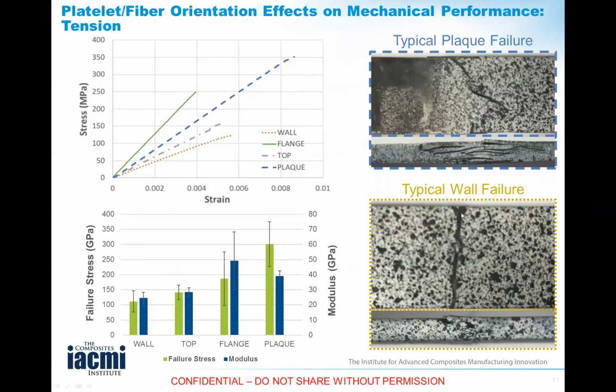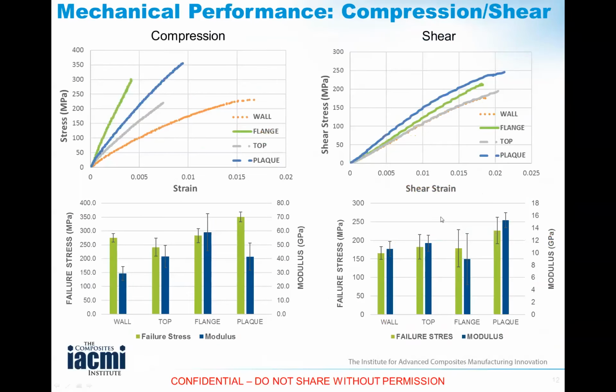So for example, the wall stress strain curve shows that the localization of the failure is very sharp through the thickness and in plane, versus in a flat plaque, where you have a lot of mobilization of failure planes that eventually coalesce to a failure surface. So this is an extremely important point. I think both the Purdue group and the Tennessee group are trying to convey to you that with these types of systems, you really need to understand spatially the orientation of the platelets, fibers, and matrix-rich regions.